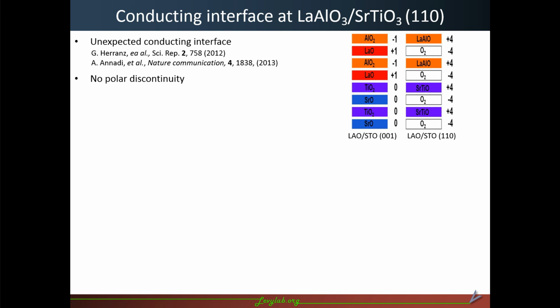But compared to the regular 001-oriented LaAlO3/SrTiO3, on the STO side, each layer is charge neutral, and on the LaO side, one layer is +1 charged and the other layer is -1 charged. So across the interface, there is a polar discontinuity.